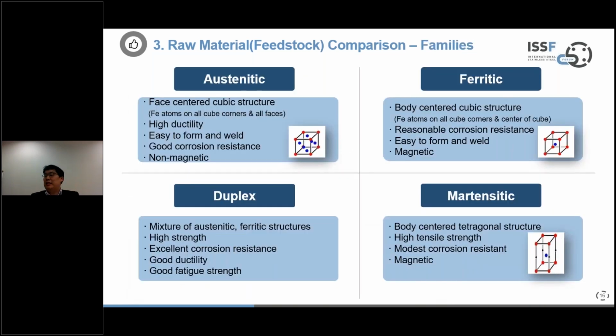Now this stainless steel is constituted of 4 families. The names are austenitic, ferritic, duplex, and martensite. And essentially, what divides them into these 4 types is how the cubic structure is made. First of all, the austenite has a face-centered cubic structure. In other words, the iron atoms are on all cube corners and all faces. This gives the austenite material high ductility, easy forming, good corrosion resistance, and it is non-magnetic.